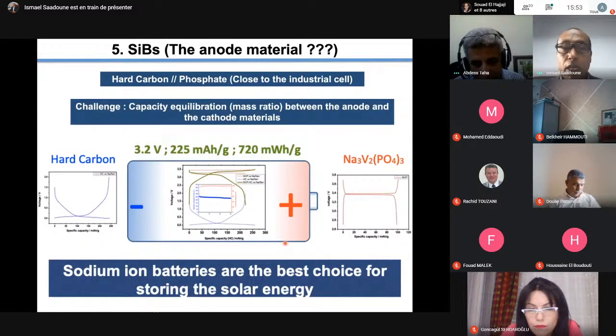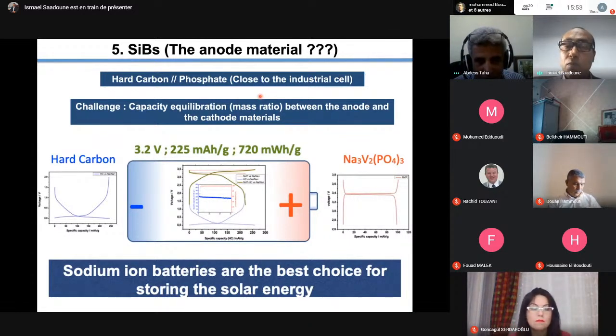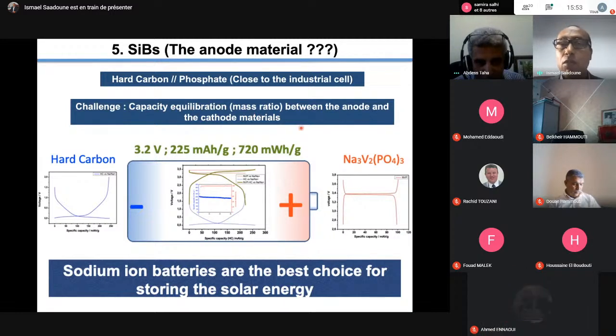What we do is use this hard carbon with phosphate to be close to industrial cell conditions. The problem was how to equilibrate the capacity between the phosphate, with its voltage and capacity, and our hard carbon. We succeeded in achieving this equilibrium, and we produced a battery with 3.2 volts and around 700 watt-hours per kilogram.